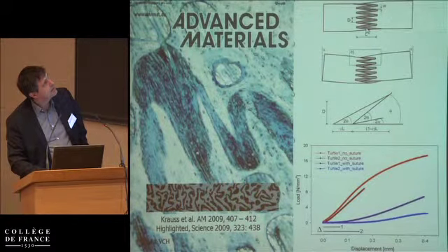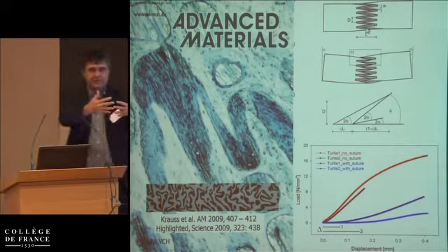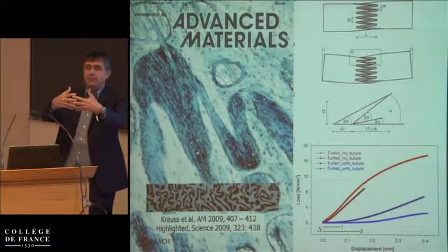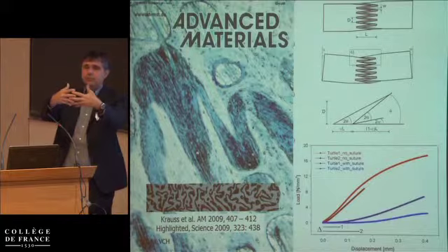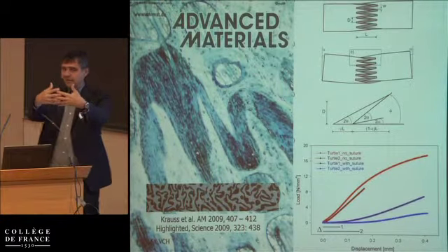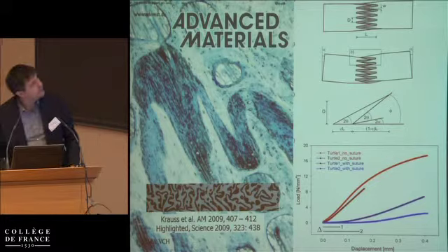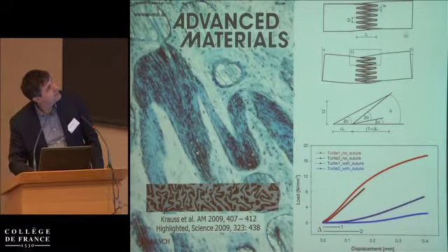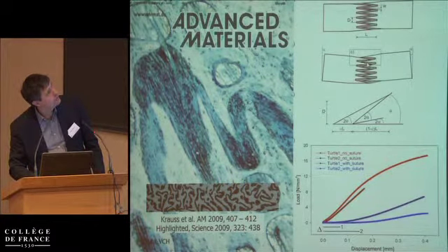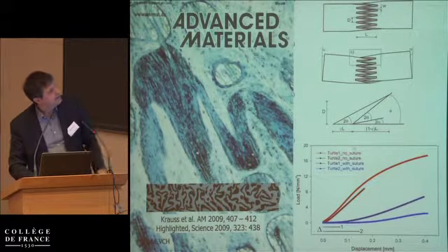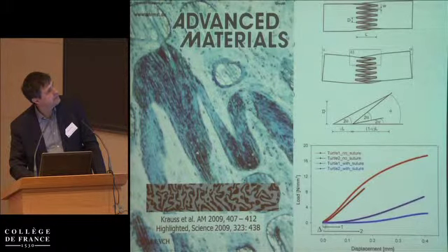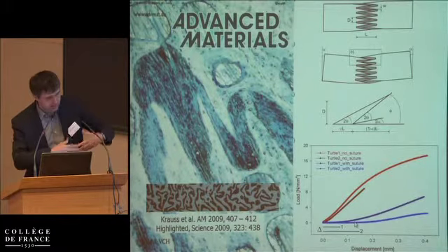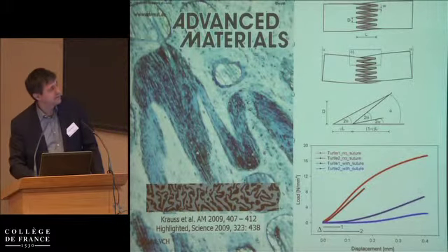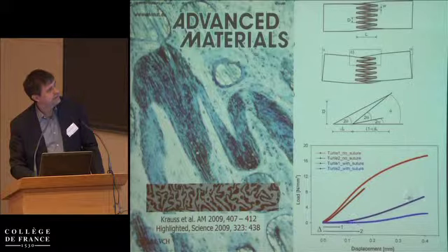This is the simplified model of it. Just take the model of my fingers. If I put a soft matrix between my fingers, you see that at small deformation, this is very soft, while at larger deformation, these fingers start to bump into each other and it gets very stiff. This is the measured behavior of bone with a suture. You see that for a while almost no load happens on bending, and only later this starts, when the fingers start to bump into each other.